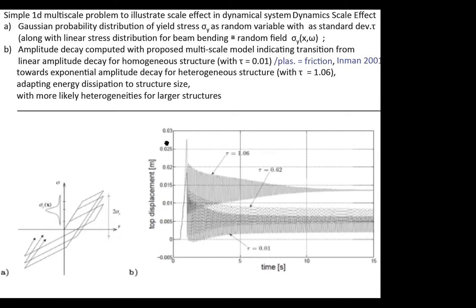And so what we did is we played with the standard deviation of this yield stress distribution as a Gaussian normal function. So if you keep a very small standard deviation, that means the structure is going to be very homogeneous. You almost have a deterministic value for each and every fiber. So basically you get something which is a linear decay of the amplitude. And this was well known by Inman, who wrote a nice book on that. When you have friction as a dissipative term, not Rayleigh, which is velocity proportional, you start having not an exponential decay, but a linear decay, and you can compute these results analytically.